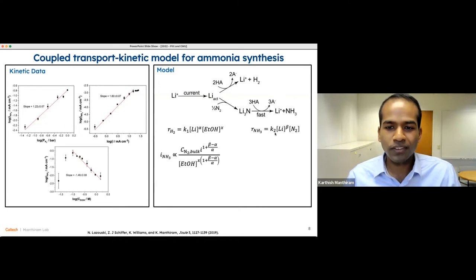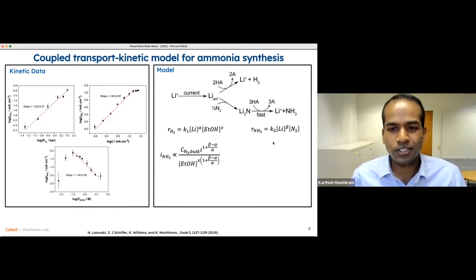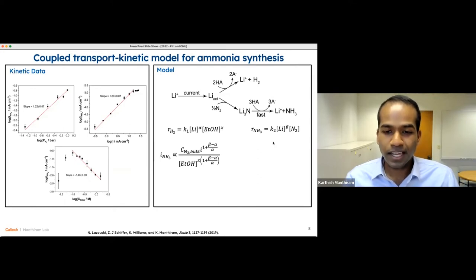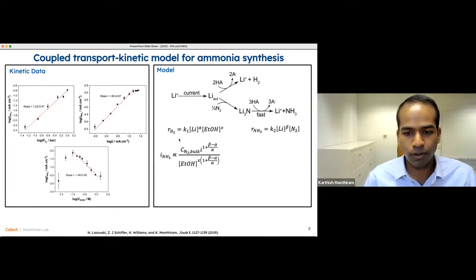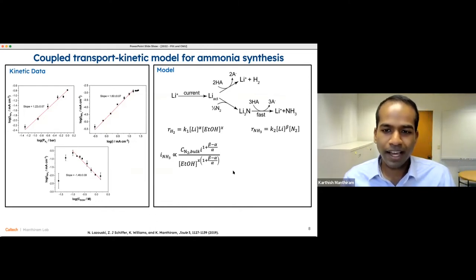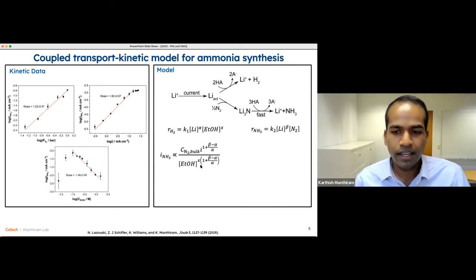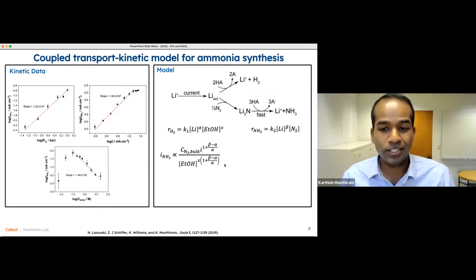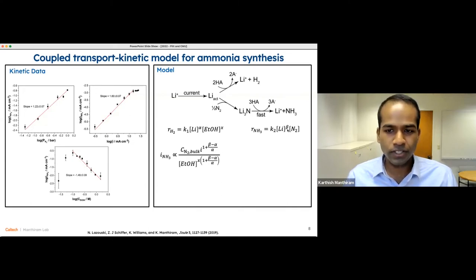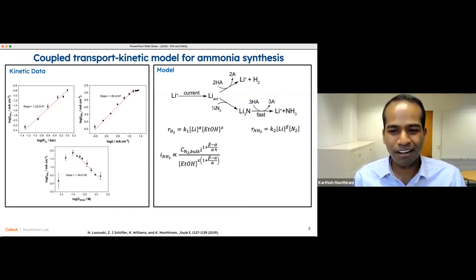We can take these two very simple rate laws, apply a steady state approximation for the concentration of lithium on the surface of the electrode, and putting those together, we end up with this expression for the partial current for ammonia. This also relies on the fact that we have a relatively small ammonia yield, which helps to simplify the denominator just by comparing terms. But you'll see a few very simple features arise from this model. The first is that even if alpha, X, and beta are integers, as we would expect for a simple kinetic model, the order dependence of partial current on current, as well as on ethanol, can exhibit a non-integer order. So integer values of beta and alpha interacting here can make non-integer orders, as we see.